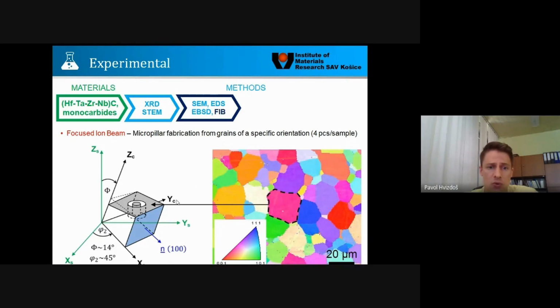Additionally, we prepared also a different kind of structure, not a cantilever, but a micropillar, as you can see on the left side. So here we also selected specific grains from which we fabricated micropillars. Those grains which were selected for the testing were intentionally selected such that their orientation was not the 001, but a slight shift from 001 towards the 111 direction with a degree of about 14 degrees. The reason why we selected that specific strange orientation, I will explain later.